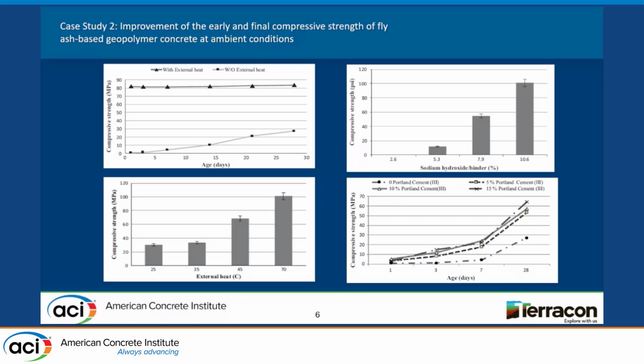And the reason why I choose Portland cement, I think, because first of all, Portland cement is available in the market, so it's easy to get. And second thing, Portland cement, when it reacts, can provide us with the heat. And this heat can be really helpful in the geopolymer concrete. And also, the reaction of the Portland cement will produce CSH plus also CH, which is calcium hydroxide. And we can see here, when we have higher alkaline concentration, the compressive strength is going to be increased. So that has really two advantages.